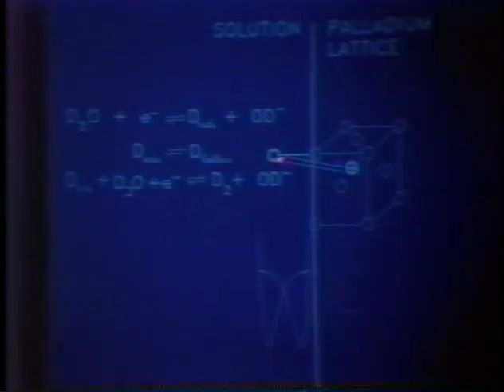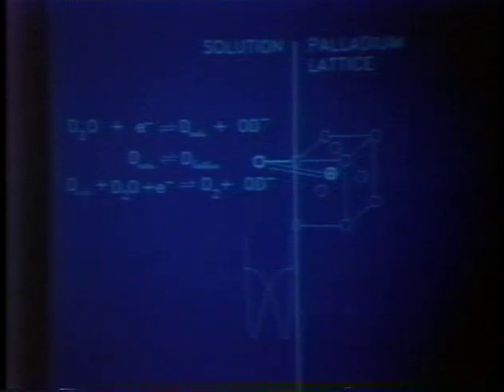then, it is well known that the atoms then diffuse into the metal lattice, but not as atoms, but as deuterons. So if we can draw a potential energy surface here for the dissociation of water into adsorbed palladium atoms, we see then that these atoms on the surface then diffuse into the metal lattice and will do so at the diffusion coefficient I just mentioned.